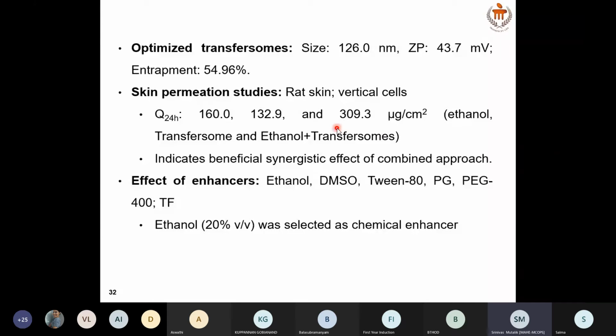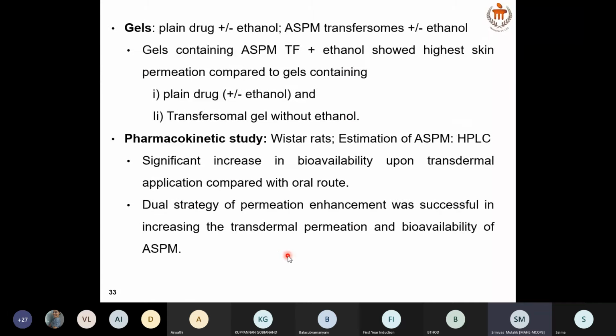So by adopting the approach of nanoparticles and chemical permeation enhancer approach, we could achieve very good permeation of the drug across the skin. It is almost double than plain transfersome, or almost double than the ethanol alone. So we also checked the effect of different enhancers, and ethanol was selected as chemical enhancer.